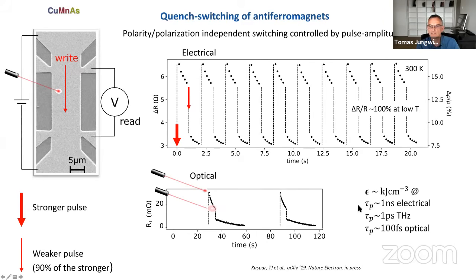And when we look at the energy densities required for switching, they are comparable for the nanoseconds, picoseconds, and femtoseconds. So indeed, we can extend switching all the way from nanoseconds to femtoseconds without delivering excessive amounts of energy. I'd like to also point out that the laser energies that are required to achieve this single pulse switching are comparable to or even lower than what's been used in single pulse switching of ferrimagnets like gadolinium iron.